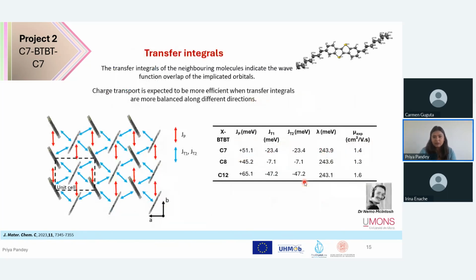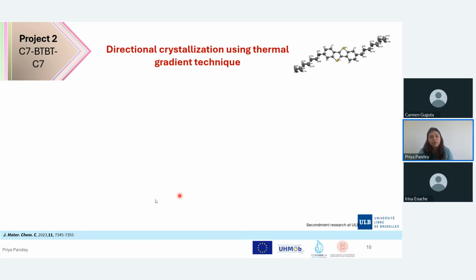Further on, moving on with the transfer integrals. In order to assess whether this molecule is a good candidate for making OFETs, we could see it computationally through transfer integrals. Thanks to Dr. Nemo McIntosh from University of Mons, he calculated the transfer integrals. The transfer integrals of the neighboring molecules indicate the wave function overlap, and the charge transport is expected to be more efficient when the transfer integrals are more balanced in different directions. Here we can see it has 2D kind of transport characteristics. And if we compare with the literature, it's very similar to the other C8 and C12. So we can expect to have a higher mobility value, just like C8 and C12. So we know that this molecule can be a good candidate for OFETs.